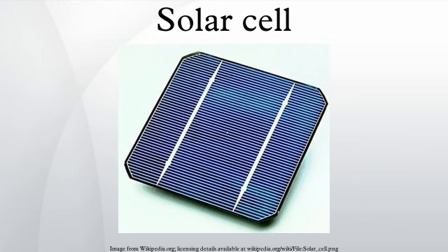Mono-like multi-silicon. This form was developed in the 2000s and introduced commercially around 2009. Also called cast mono, it uses polycrystalline casting chambers with small seeds of mono material. The result is a bulk mono-like material that is polycrystalline around the outsides. When sliced for processing, the inner sections are high-efficiency mono-like cells, while the outer edges are sold as conventional poly. The result: mono-like cells at poly-like prices.